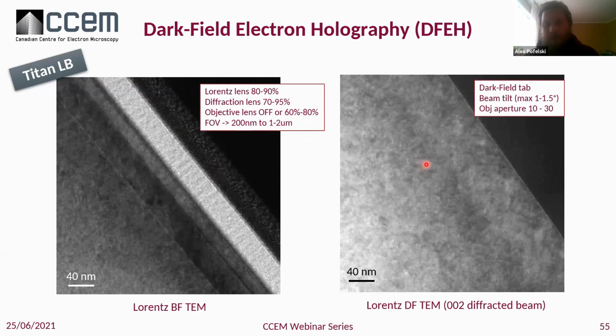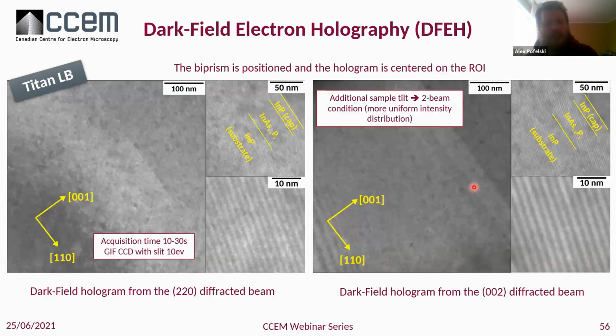Then on top of that, you go to the dark field tab, beam tilt your sample, so max 1.5 degrees. You don't have that much room in the beam tilt in the Lorentz mode, because then the beam hits the side of the column. Then use the objective aperture 10 or 30, something that just isolates your diffracted beam only into the signal. This is a typical Lorentz dark field image of the 002 diffracted beam. And then you finally put your biprism on top of that to record those holograms.